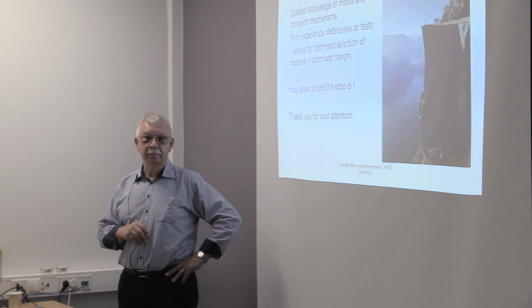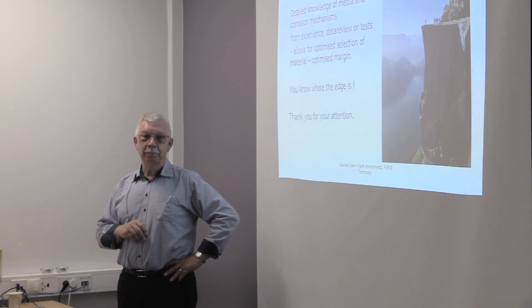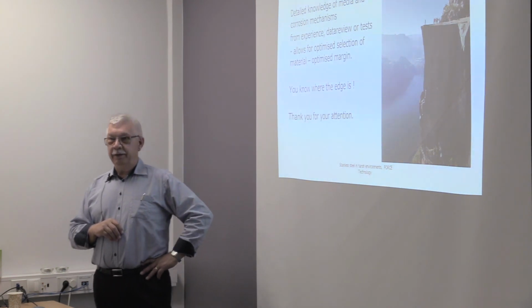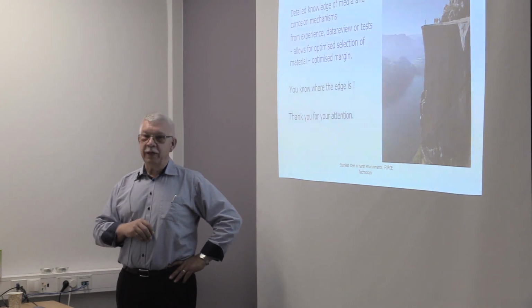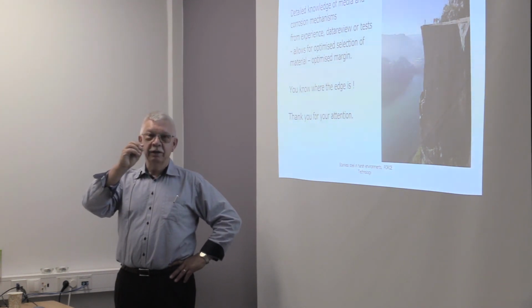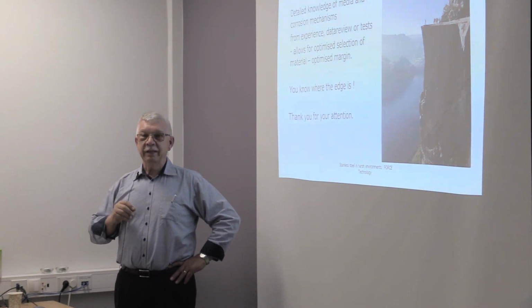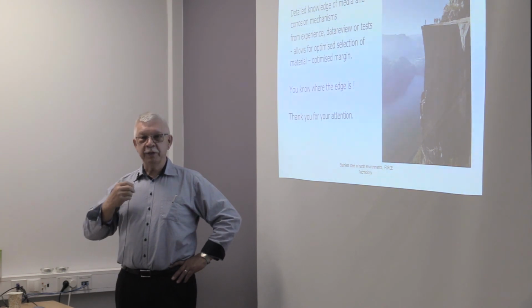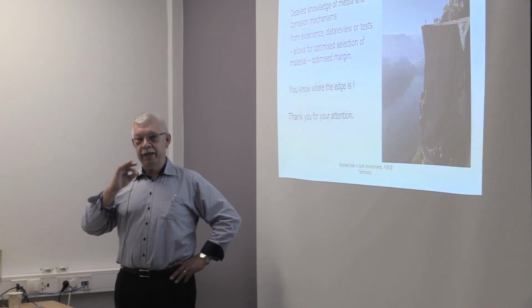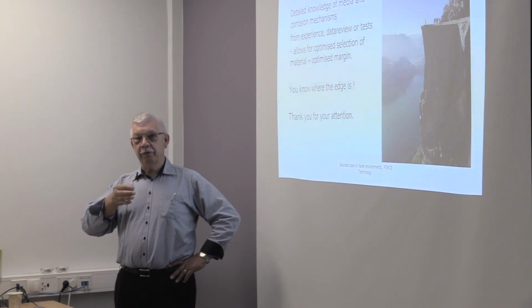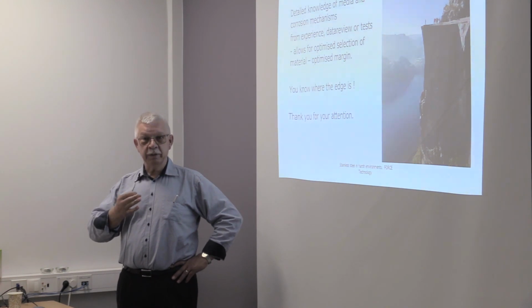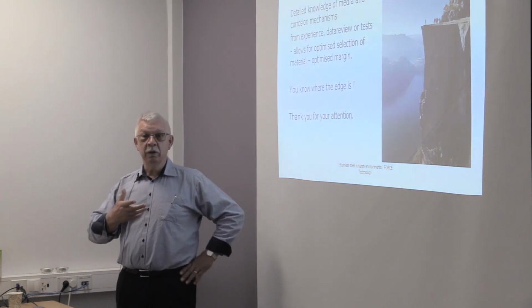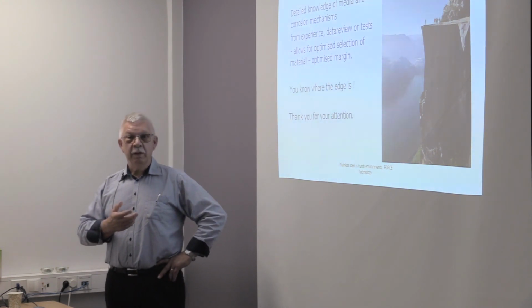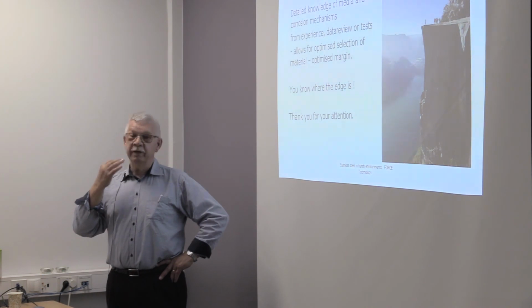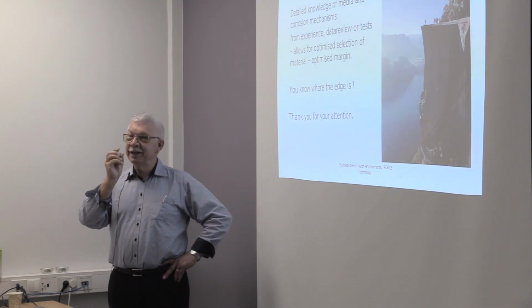When you use an orbital welding machine, you don't have a filler material, then this weld would be lower in corrosion class than with filler material. Yes, but when I think orbital machines, I think very thin walled piping, and it's a very fast process. So our experience is even with a very, very qualified hand welder, the amount of weld metal will be lower in the orbital welding. The amount of heat tint on the sides will be lower in the orbital welding. So it's possible to do a very, very good hand weld, but it will always be slightly better in an orbital weld.